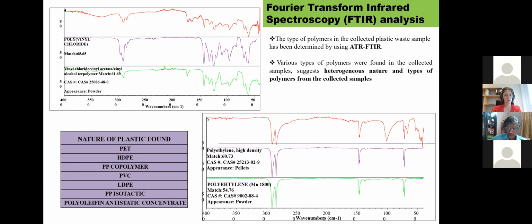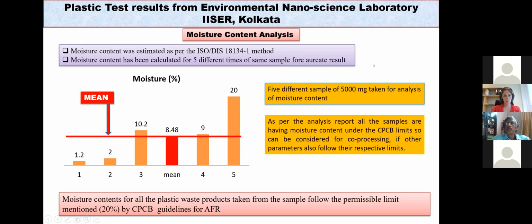We have sent the plastic samples to the IISER laboratories. So this slide shows the analysis of the polymer content and identifying the types of plastic present in the samples. We have done the FTIR analysis. Their FTIR graphs have been shown between the transmittance and the wavelength of the sample. So identifying the peaks of the sample's molecular compositions, we have observed that the most predominant plastic types are PET, HDPE, polypropylene, PVC, etc. So the next slide shows the moisture content which has been tested through international standard.